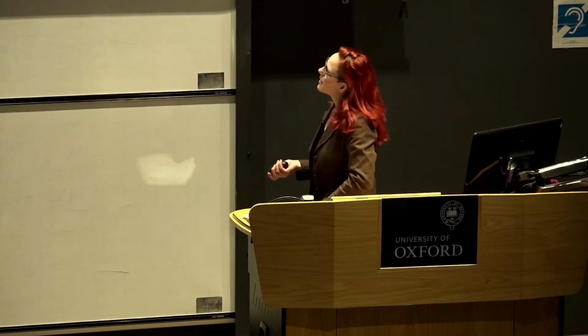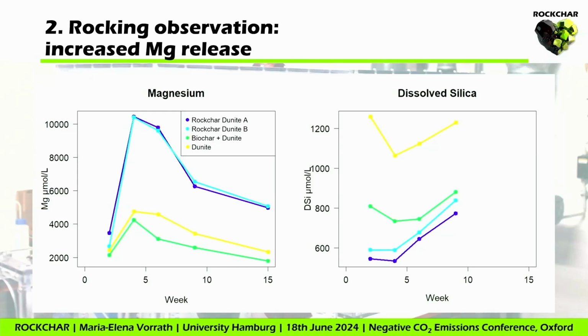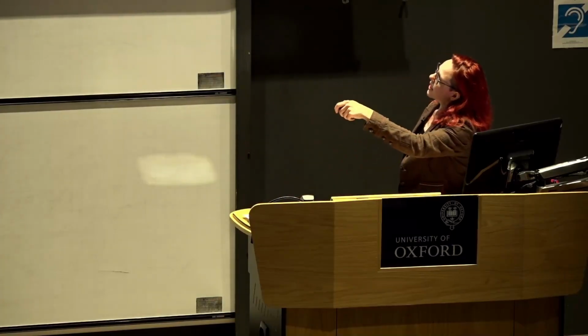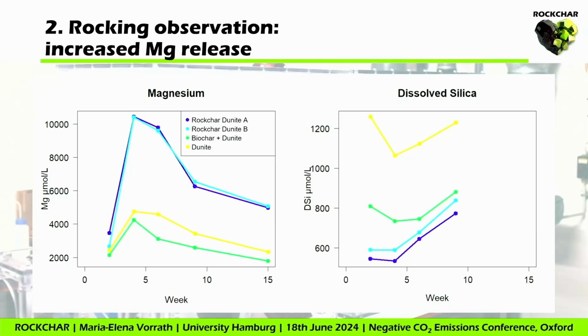Okay, and then the second observation I made is I have an increased magnesium release. Again, I'm comparing ROCKCHARs against biochar mineral co-deployment and the mineral deployment. This time it's dunite. The blue graphs you can see, this is ROCKCHAR based on dunite, and they release much more magnesium compared to pure dunite. When dunite weathers, you expect a certain ratio of magnesium to silica, and if you look at magnesium and silica, the blue curves, the ROCKCHAR based on dunite, is releasing very small amounts of silica, so it should release much more because it's also releasing a lot of magnesium.